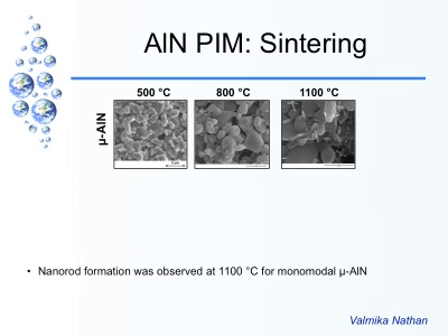You know, this is about 2 micron in dimension. You can't see it very clearly on the screen. So the same 2 microns over is what you end up seeing over here. And you can see that these rods that are beginning to develop are in the nanoscale. When we did a chemical analysis of just the regions with the nanorods, we found that it had yttria and alumina as the constituents. So that is the liquid phase forming, and when it is then beginning to solidify, it seems to, for some reason, make these kinds of rod-like structures.